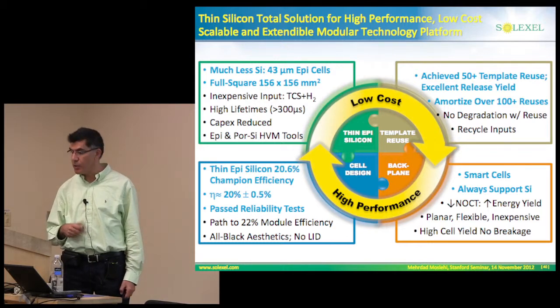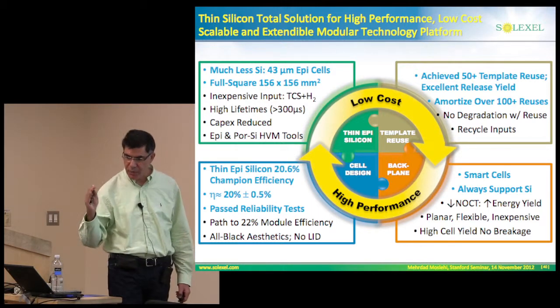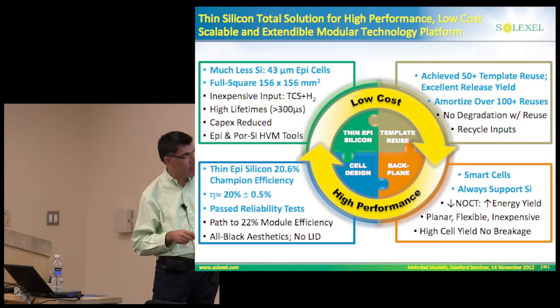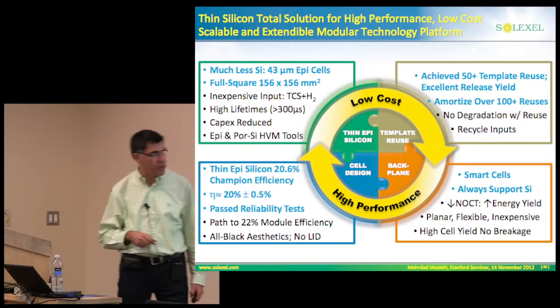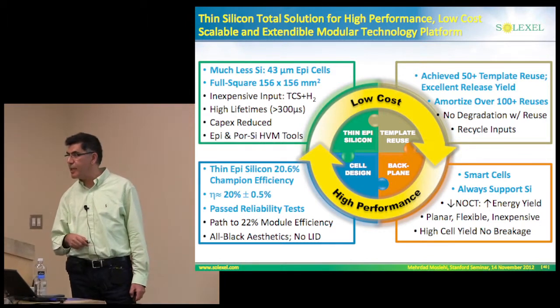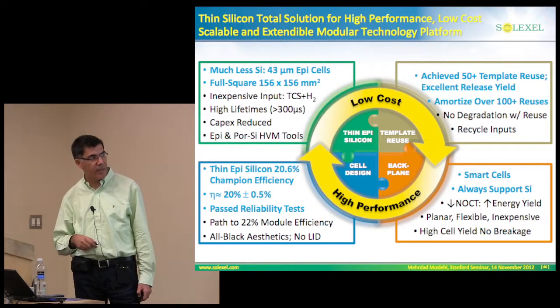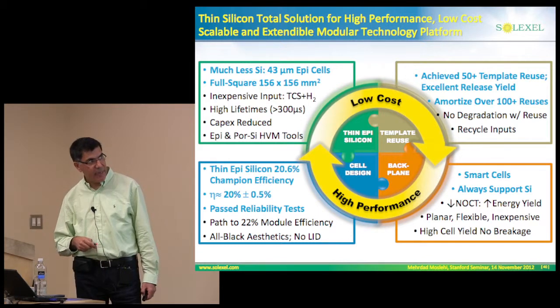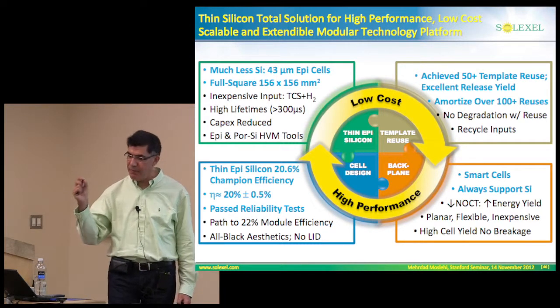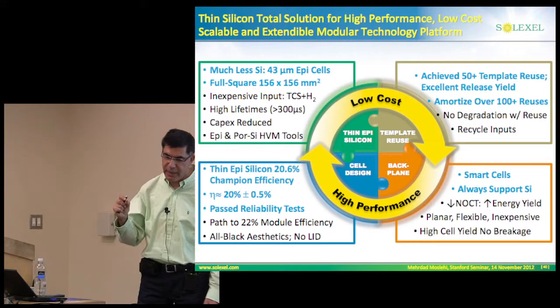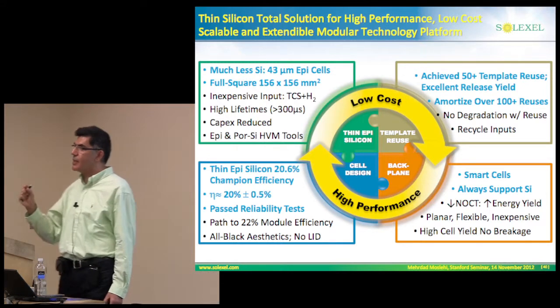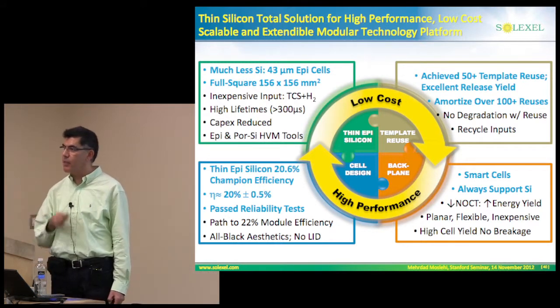Today we have a world record champion efficiency for thin silicon, 20.6% full area, mean efficiency 20%, tight distribution, excellent reliability results to date. So very encouraging as we move towards the commercial phase. And the combination of backplane and template enables us to always support silicon. So we have a very robust solution to the thin silicon handling and processing problem with our technology.